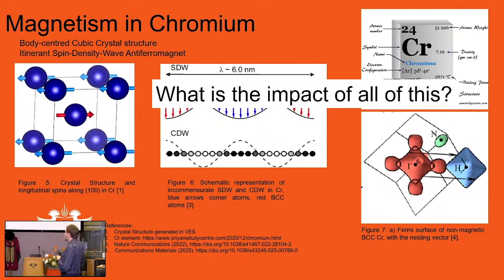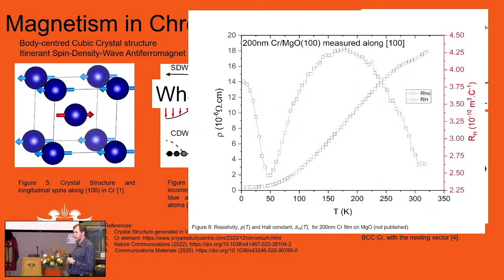Then what's the impact? What do we measure? How do we see what's happening here and what happens in this gap? Of course, one can measure this quite accurately with ARPES. There's a recent paper on chromium where they've done this in Nature. Well, how do we see it in the lab? Here are some results that we've measured with our new equipment, the NEP equipment. This is a very thin layer, 200 nanometers of chrome, on a very highly orientated substrate because we want a particular direction.